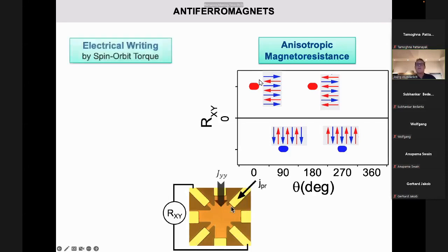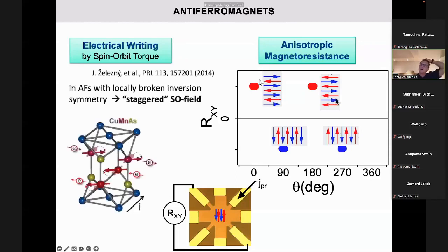And if you have the way to switch by some means, and this is actually the coupling between the spin and the orbital degree of freedom of electrons, the antiferromagnetic orientation of such a system, in a way that you can do it by 45 degrees with respect to your probe current, you can indeed distinguish those two states if they are, say, in this horizontal alignment or in this orthogonal alignment here. Yeah. However, you cannot distinguish reverse states. They are unfortunately identical.